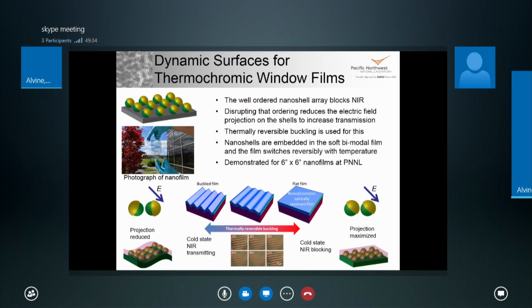And instead of getting infrared reflecting, you get essentially infrared transmission. So we incorporate a buckling transition, or a wrinkling, into the film, where in the cold state the film is wrinkled and the shells are all misoriented, and infrared light comes in. So you get that beneficial heating from the solar heating into your room to warm it up. But when the window film heats up and the room is hot, you no longer want that solar heating. The film has now expanded and is flat, so you get a well-oriented film that can then reject the infrared light. So it can switch reversibly based on the temperature of the window, between a buckled film that's allowing infrared light in, and the flat film in the hot state that's blocking the light.